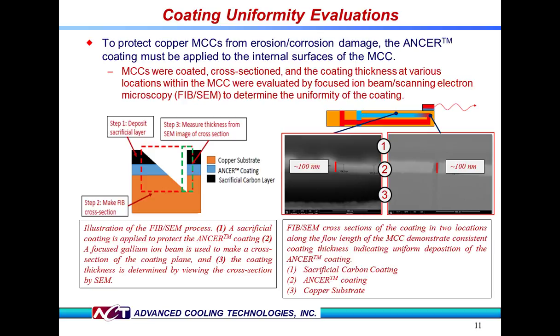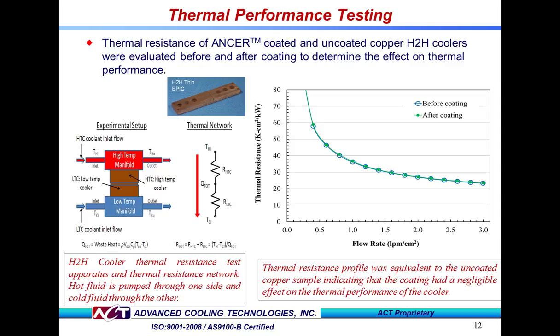The top diagram shows the location in the microchannel cooler where the samples were taken. The actual SEM images are seen below that. The darker gray on top, number 1, is the sacrificial layer. The lighter area in the middle, where the ANCER coating is, number 2, and the copper base is below that, number 3. As can be seen here, both locations have thicknesses of approximately 100 nanometers. Of course, the entire coating is not at precisely 100 nanometers, but good uniformity, plus or minus 25 nanometers, has been achieved.